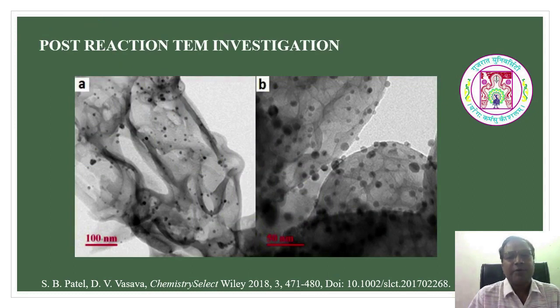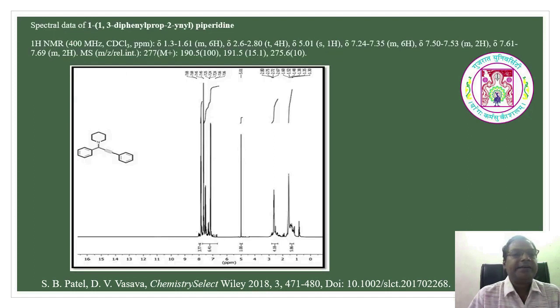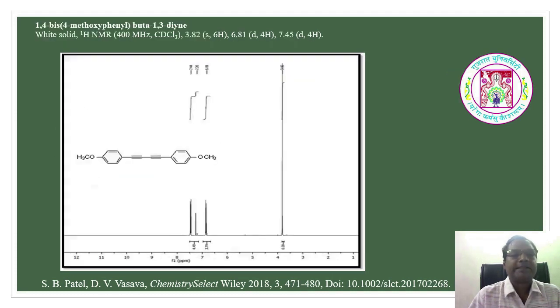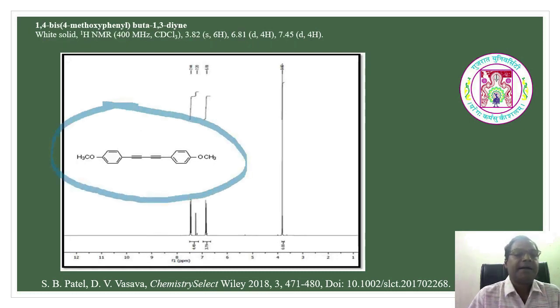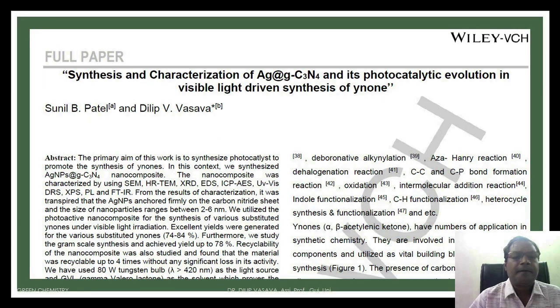Here the post reaction TEM investigation is given. So TEM analysis of the post reaction after the 7th run is taken. So fewer Ag nanoparticles are lost during the reaction. And finally the product propargyl amine is produced, that is confirmed by the 1H NMR, and the homocoupling reaction took place, and that also was confirmed by the 1H NMR and the mass spectra.